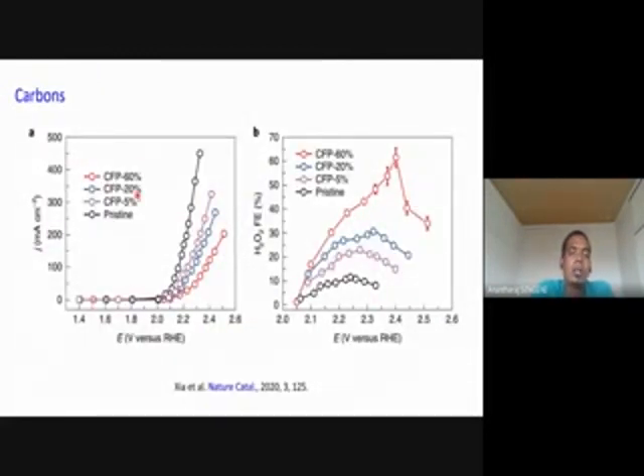What they did was, they took carbon fiber paper and coated it with PTFE, a binder which is highly hydrophobic, as we know, with various percentages: 5, 20, 60%. They noticed that with increasing amount of PTFE, which means increasing hydrophobicity, the water oxidation current density lowered, as you can see here, but the H2O2 selectivity increased.